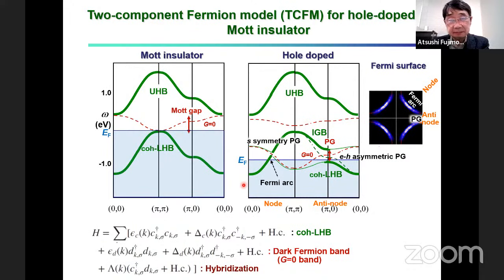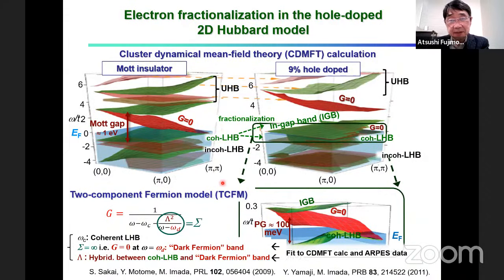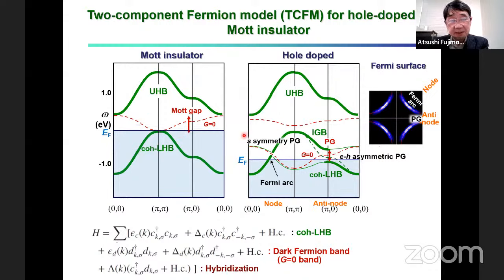And this is a more schematic drawing of the upper Hubbard band, lower Hubbard band, the coherent part of the lower Hubbard band, and the dark fermion, with divergent Green's function. In the hole doping range, the coherent lower Hubbard band and the dark fermion band hybridize with each other and open a gap in the antinodal region. That's how the pseudo gap is opened.